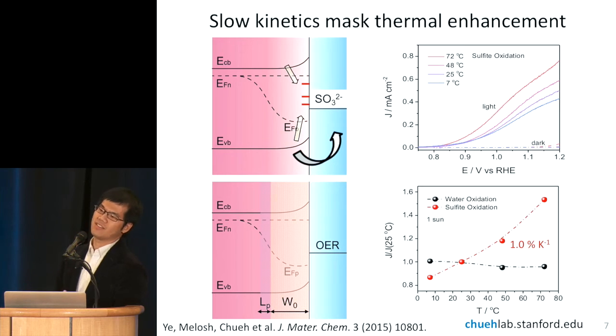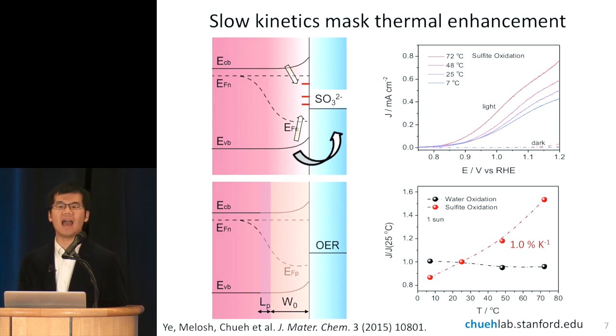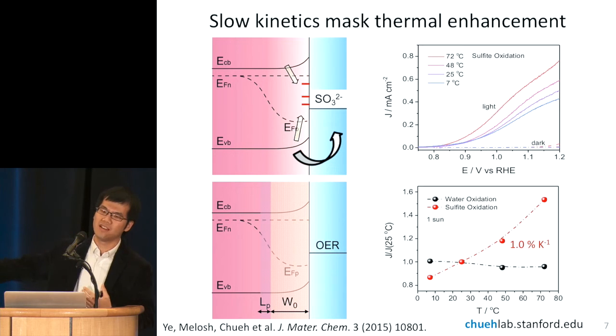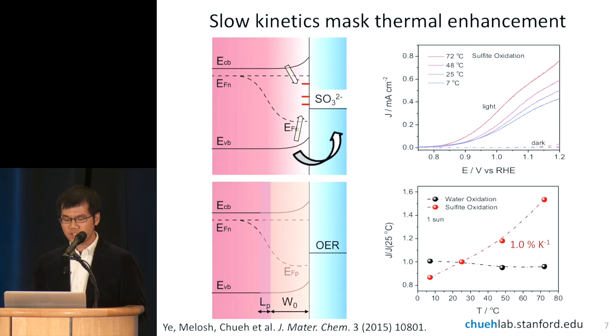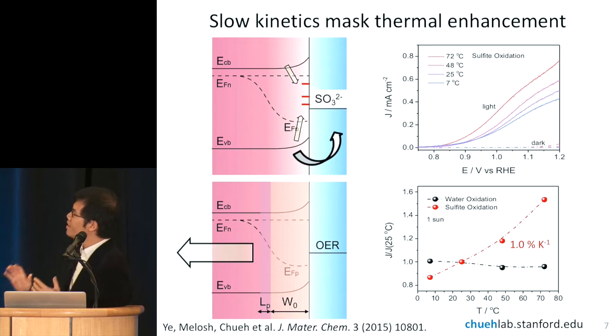And the space charge region is not strongly activated by temperature, because the mobility really governs how thick the minority carrier diffusion length is, and it only changes the space charge region negligibly. So the second idea we had was, can we increase the minority carrier diffusion length so that we can absorb more light in a region in which the temperature enhancement will be more noticeable?